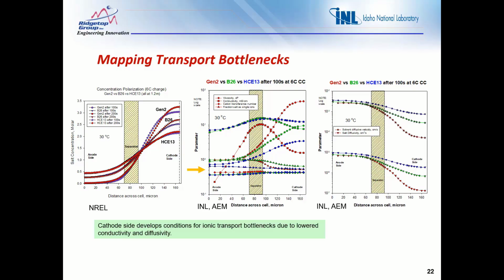So for the Gen 2 system, which is a carbonate EC, EMC, LiPF6, if we follow the red squares, we see that the conductivity becomes very low toward the anode side. And this is a log scale, so please note that there's about 3 orders of magnitude represented in this plot. So anode side Gen 2 electrolyte has very low conductivity, goes up, and within the separator is where it becomes its maximum value. And then as you go toward the cathode, and the cathode becomes basically underutilized because there's a stagnation of salt near it or within it, the conductivity drops again to fairly low values.